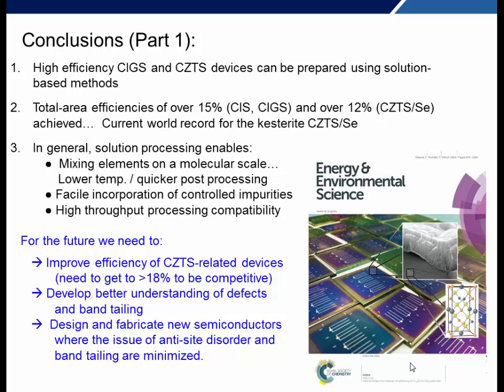devices. I think what's really exciting about this is the fact that usually solution-based deposition is thought of as an approach for low cost at the expense of performance. Here we see that high performance can also be achieved using solution-based deposition. Some of the advantages of solution-based deposition include mixing on a molecular scale, which enables lower temperature and quicker processing. The incorporation of impurities is also very easy, which can control grain growth, and the processes can be quite high